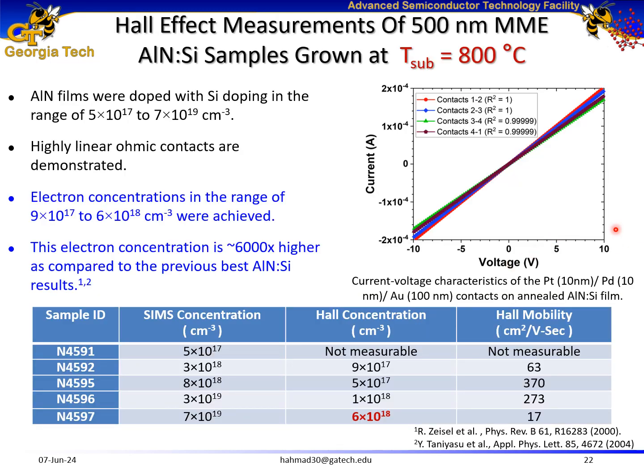So I utilized the high crystalline conditions of MBE and I grew silicon-doped aluminum nitride films in the doping range of 5 into 10 to the power of 17 to 7 into 10 to the power of 19 per centimeter cube. And I achieved a high electron concentration of 6 into 10 to the power of 18 per centimeter cube, which is 6,000 times higher as compared to the previous best electron concentrations in silicon-doped aluminum nitride.